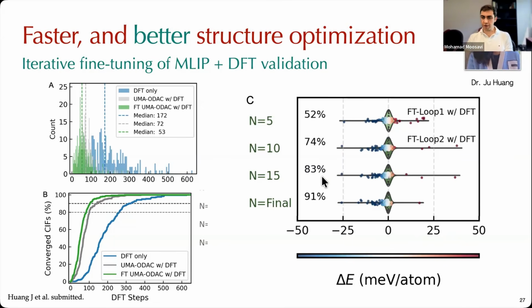So based on these observations, with this benchmarking we did, we decided to limit our DFT steps to 15 to save budget, because if you let the DFT complete the work, it goes on average, or on median, about 53 steps. But those 53 steps don't add much. For 83% of materials, you already get it right with 15 steps.